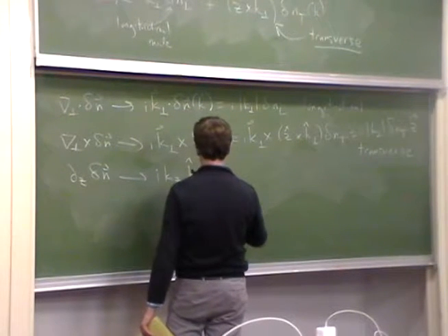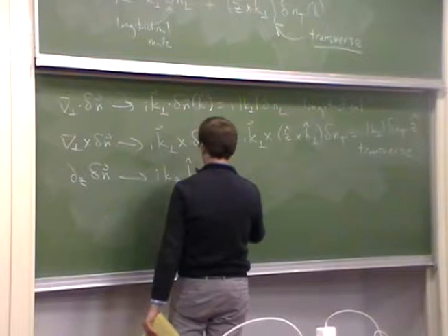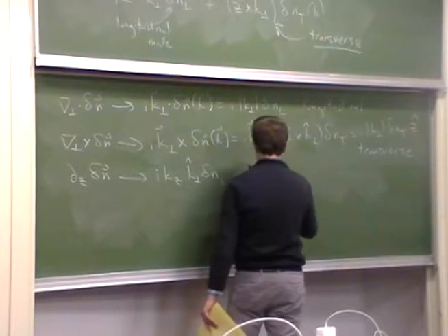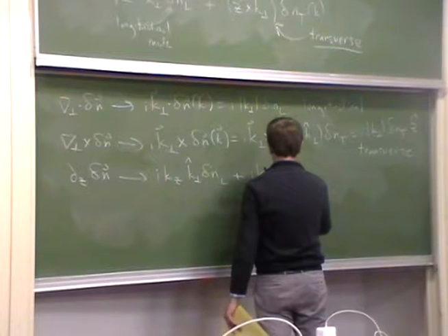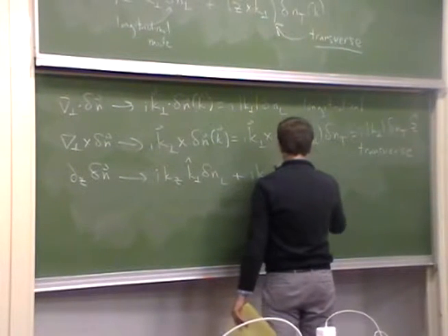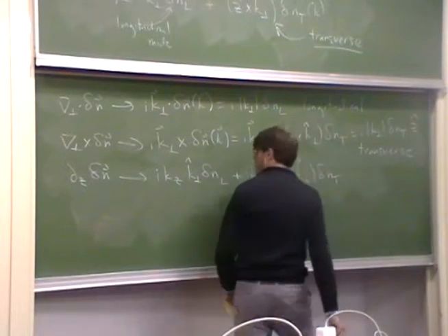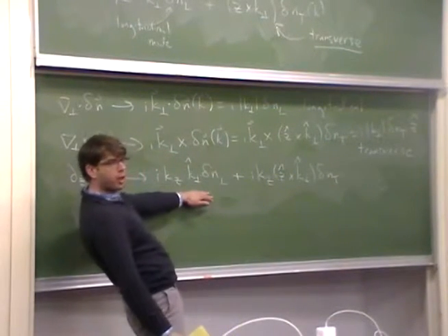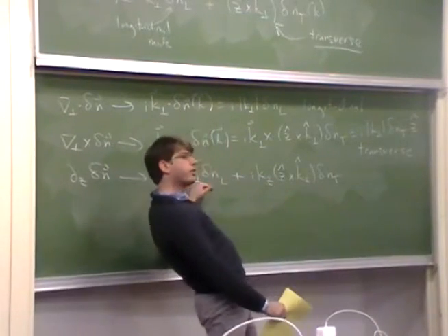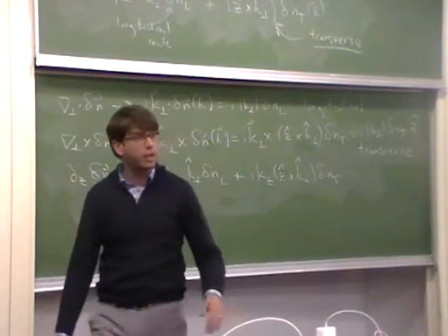Okay, so both modes generate bending, although in perpendicular directions. So both longitudinal fluctuations and transverse fluctuations give you bending. So that means that the energy cost for both polarizations should have K3 in it, while only the longitudinal mode will have K1 in its cost, and only the transverse mode will have K2.